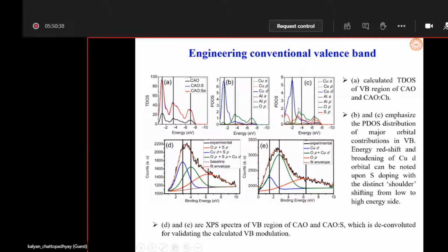Look at this one. See, the copper d contribution is compared to this B picture. You can just compare the copper d contribution in these two systems. So when sulfur is introduced, you can see that the blue line extends to more than 5 electron volt, which is also experimentally verified. Look at this. This is the copper d, the blue one. So it is about 2.8. But now when sulfur is introduced at the anionic site, it extends to more than 5. So this is a direct proof that valence band dispersion has been achieved by the anionic site doping.